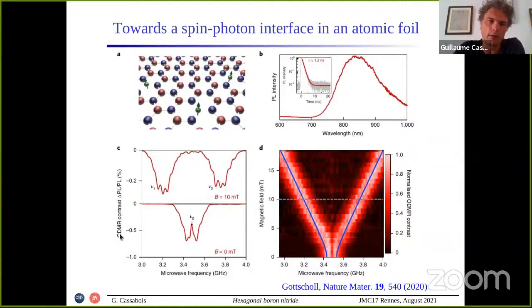...the intensity of the optical emission depends on the magnetic field and the microwave frequency, the typical degrees of freedom used experimentally to reach a spin photon interface. The originality here is that the defect can be extremely bright, emit a lot of photons, and it is available in a crystal that can be as thin as an atomic foil, basically a honeycomb lattice of HBN.